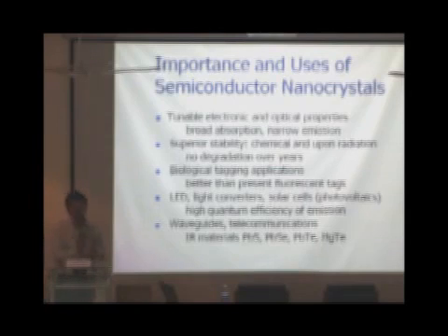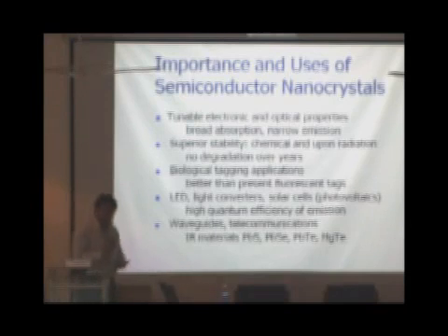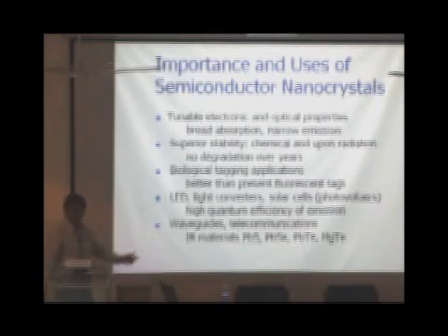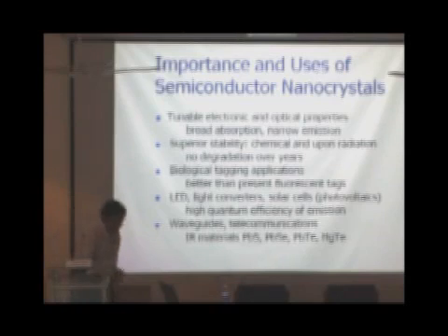That means I can excite these particles at any given energy, of course above the band gap, not below the band gap. So I can excite it at any energy, but I'll get only one single very sharp emission. So if I have a collection of particles lying over there, I can excite all these particles with one single source, somewhere in the ultraviolet, let's say. And then they're going to all emit. So that gives me a possibility of something called multiplexing, or studying different colors at the same time.